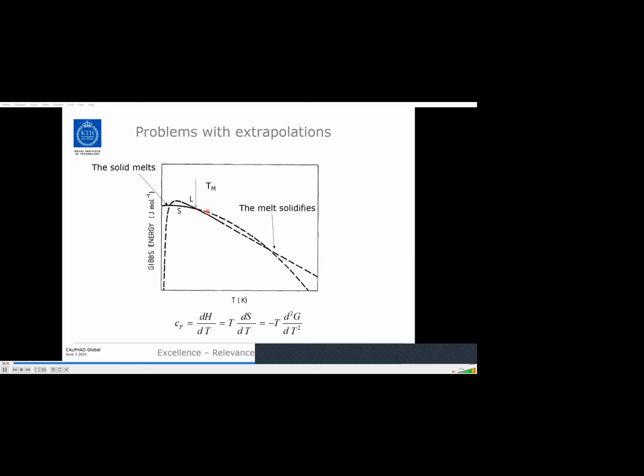So here the Gibbs energy of the solid is higher than that of the liquid, and the liquid is more stable. But then we find that there is an intersection also at low temperatures, which would mean that the solid would melt at this temperature, because the solid now has a lower Gibbs energy. And in a similar way, there is an intersection at high temperatures, which means that the melt would then solidify at high temperatures. And those two predictions are, of course, absurd, and they are just based on a bad extrapolation of the experimental information.